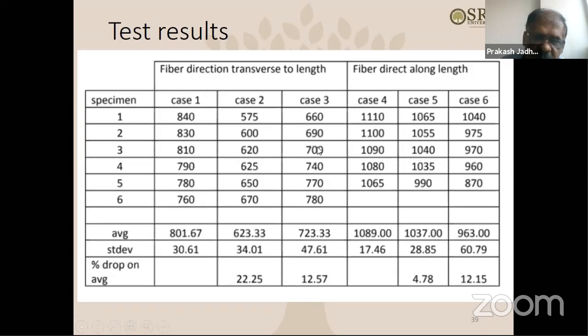it's going to affect. So here also, if you see case three, it's showing like a 12% drop from the failure load. Okay. Drop in the sense they are failing earlier than these coupons. So these coupons are good, but these coupons are failing earlier than these coupons, which is not good. So then what to do basically? Then you have to play around with the designs, like these coupon designs, ply drop designs. So fiber direction along the length, there also you see it is like 4%, 4.7% drop, 12% drop in these cases.